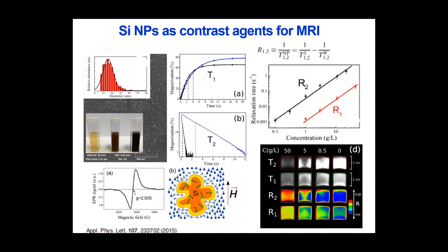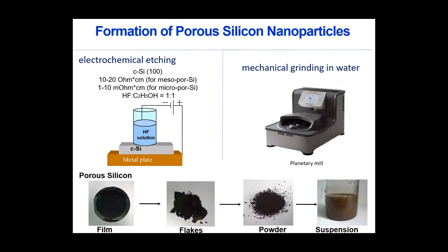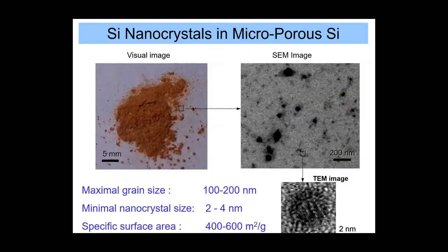In the next part of my talk, I will speak mostly about the photo properties of silicon nanoparticles. Silicon nanoparticles were prepared by two main methods. The first is the traditional method of porous silicon formation combined with detaching of porous silicon films, grinding in water in a planetary mill — a strategy proposed many years ago by Leigh Canham. We obtained concentrated aqueous suspensions of porous silicon nanoparticles containing many different particles, including microporous particles that are already luminescent. We can find very large aggregate particles and also individual nanocrystals with nearly perfect crystalline lattice.